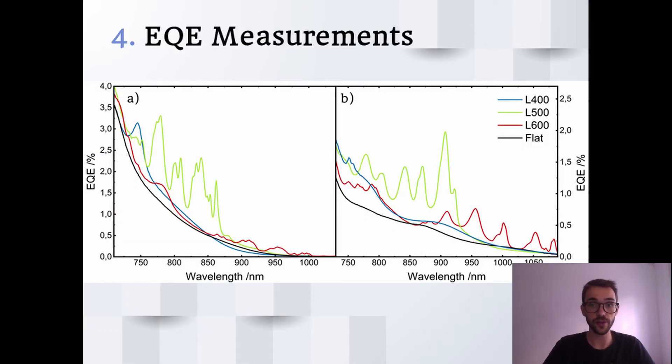Measuring the external quantum efficiency, we see that while the flat devices rapidly fall to zero, the nanostructured devices show several peaks depending on their lattice parameter.